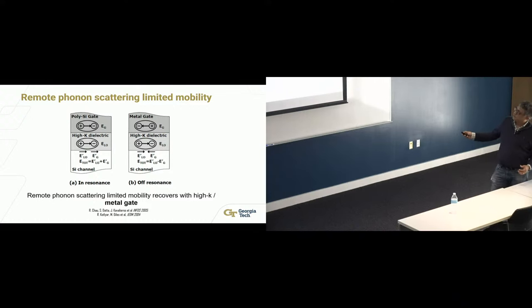On the other hand, if you use a metal gate, and this works only if your high-K dielectric is thin enough, it is not going to work if you make it 30 angstrom thick. For a thin enough high-K dielectric, the metal gate can respond at a higher frequency. If you remember your high school or freshman physics, if you have a charge and an infinite metal plane, it can induce an image charge. But this is not a static phenomenon, it is a dynamic one. What we found was that this image dipole can partially cancel this high-K phonon. It can potentially mitigate, not eliminate, the effect.